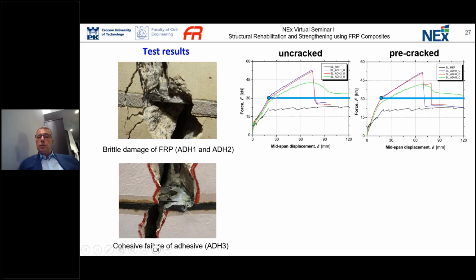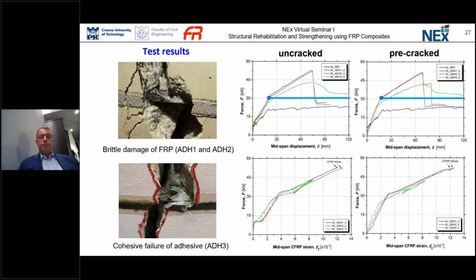And this blue and red curve in both cases represent the adhesive with stiff epoxy resin, and this green one represents polyurethane. As you can see, practically this system does not differ so much, but in the case of polyurethane adhesive, we have the post-failure resistance that can improve additional safety to the structure.